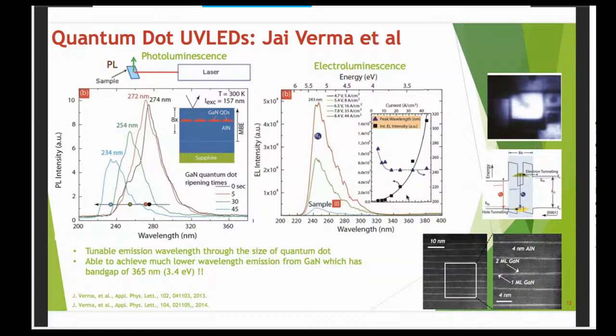Another thing we used to confirm that we were actually growing the correct thickness of the gallium nitride was transmission electron microscope. A transmission electron microscope works like a film projector. You put a film in the front and you shine light through it, and on the projector screen, you see whatever was on the negative being projected onto the white screen. Similarly, in the transmission electron microscope, you create a very thin sample that you want to look at, and you shine electrons through it. And you have a screen below that captures these electrons.